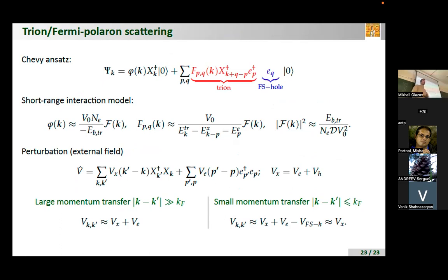So the old work of Pikus, and I think there were a lot of papers at about the same time, was more or less about the Mott transition for the exciton. You have, rather than a shallow Fermi sea, a Fermi energy much larger than the trion binding energy, so you can forget about three-particle correlations, and then you indeed need to make your exciton orthogonal to the Fermi sea. In this case, the binding energy of the exciton vanishes, thus the oscillator strength vanishes, and at some point the exciton dissociates. And then you have this Mahan singularity, which is probably not very easy to observe.